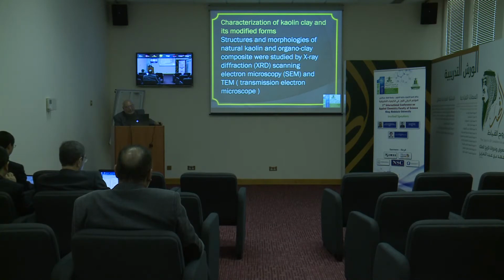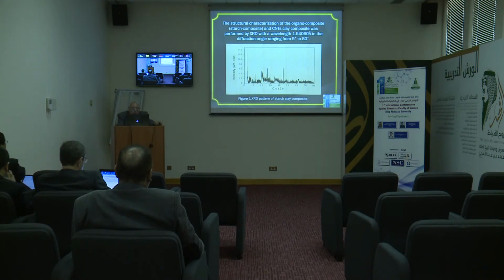Characterization of kaolin clay and its modified forms: structures and morphologies of natural kaolin and organic clay composite were studied by X-ray diffraction, XRD, scanning electron microscope, SEM, and TEM, transmission electron microscope. The structural characterization of the organocomposite, starch composite, and carbon nanotubes clay composite were performed by XRD with a wavelength 1.54 angstrom in the diffraction angle ranging from 5 to 80 degrees.